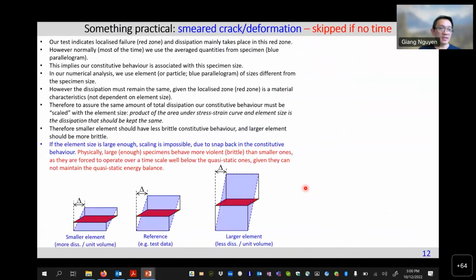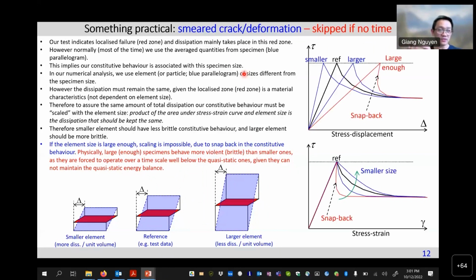The smeared crack, in the loose sense, is to scale the properties of the material so that in the end, our final element or our integration point with the given size is able to reproduce the dissipation energy, the fracture energy, that we got from the test and imposed on the model. So that's the case. We're scaling artificially the behavior of the model to get something at the end. Practically it's very useful. I used that a few times as well, but if you go to large scale, it's not scaling well. Scaling to very large scale, we will talk about that later, is very different and very challenging.